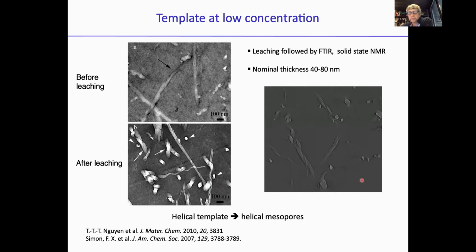And on this little movie, you can see it's just defocusing. If you follow the shape of the objects here, you can see the trace of helical objects. And these white objects here are just objects that run across, perpendicular to the section. And when it's defocusing, you can see it forms like a vortex, showing that all these objects are more or less helical tapes. So we succeeded in making a good replica, meaning that with high resolution, we start from a helical template and we obtain a helical mesopore, which means that the resolution of this molding is about a few nanometers. So we are quite happy with this.